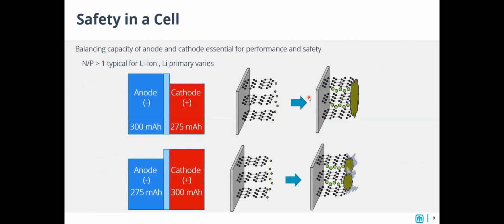Another aspect is the actual design of the cell itself. This is especially true for rechargeable lithium ion batteries, where typically what is done to improve safety is to undersize the cathode capacity compared to the anode capacity in order to have proper performance. What happens if we undersize the anode compared to the cathode is that we can fill up the graphite anode with lithium, and then there's still lithium in our battery that will plate onto the surface of our anode instead of intercalating inside. That plating can grow lithium dendrites, which can short the cell. All of this needs to be avoided for proper use and to avoid catastrophic failure.